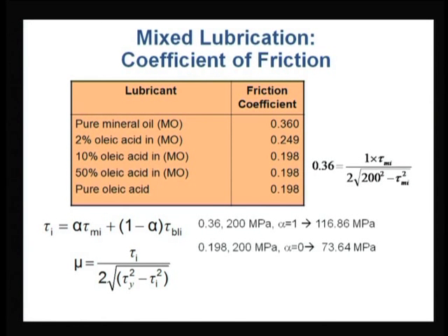Mind it, it is in megapascal, it is not in kilopascal, it is not in pascal. When we talk about fluid film lubrication, we were talking about only pascal, not even reaching kilopascal. When we are talking about EHL and the viscosity thickening effect, then there was a possibility of some kilopascal, say 1-2 kilopascal. But in the absence of those lubrication mechanisms, when you are talking about boundary additives, just a monolayer or very thin lubricant layer on a surface, maybe some nanometers, the coefficient of friction is reasonably high, but the whole surface is covered with boundary additives.